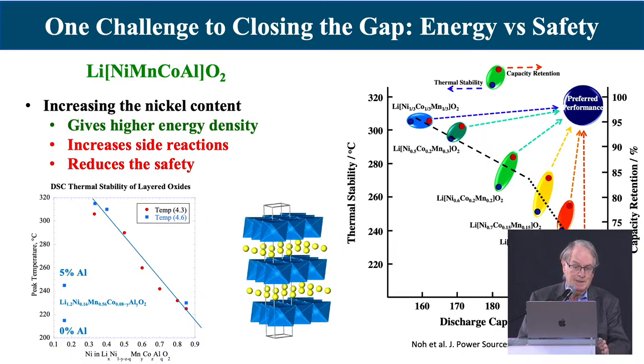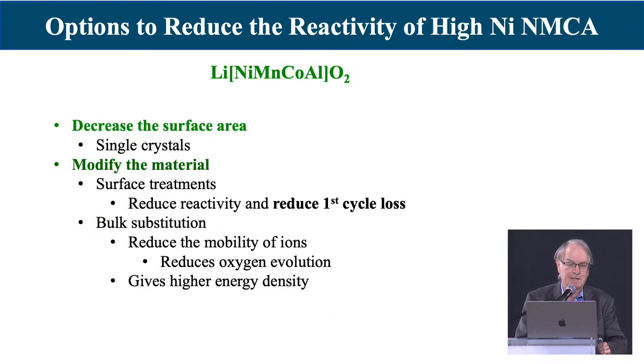So our challenge is really to use as much nickel as we can, stabilize these materials so they don't release the oxygen and get into that blue circle at the top there, which is 100% capacity retention, no loss of oxygen and long life. And on the bottom left-hand side, I show similar data, different charging potentials, a number of other different parameters, but the same thing: that straight line is directly related to the nickel content, so it's totally nickel content that determines stability. So what can we do to stabilize these materials?